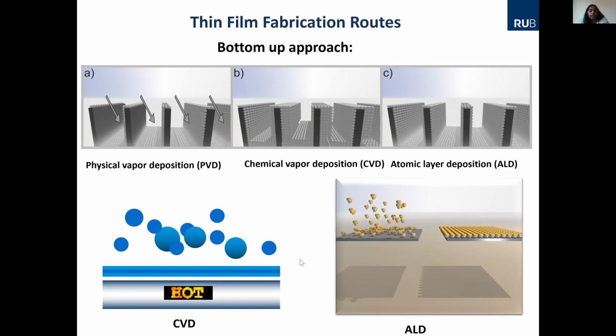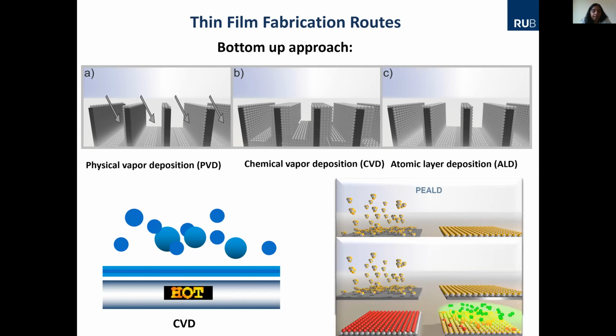Okay. Unlike CVD, in ALD, you also have precursors, but you don't mix the precursors. You use the surface properties, basically a chemisorption of the precursor on a surface that will interact, and you have an exchange reaction taking place. I will show in my next slide how exactly it works. And then you have a sort of pulse and purge process where you pulse one precursor, adsorb on the surface, allow it to react with the functional groups. And this I can show you better in the next slide.